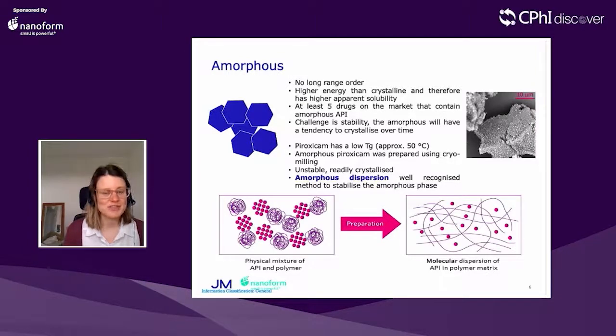However, a challenge that we see quite commonly with just looking at the amorphous API on its own is that it will have a tendency to crystallize over time, which obviously is a huge disadvantage if we're looking at the performance of that drug product over its shelf life. In fact, this is what we saw when we looked at the piroxicam. We found that piroxicam has a relatively low glass transition temperature of around 50 degrees. When we prepared amorphous piroxicam using cryomilling, we did see that once that material was exposed to ambient conditions, it did start to crystallize.